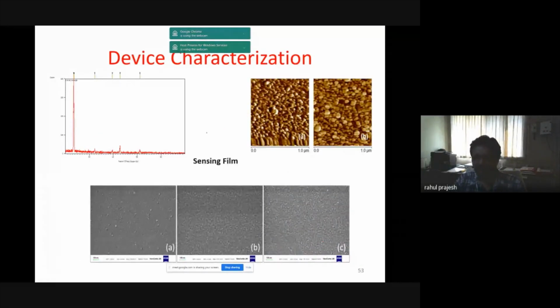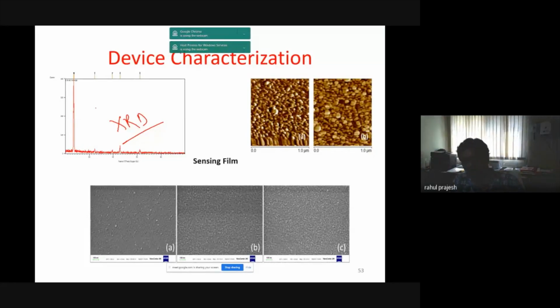Then comes the characterization of your film. In the film, what can you check? You need to first check your crystallographic orientation using XRD. XRD will tell you which planes are present. Is it a single crystalline film, a polycrystalline film, or an amorphous film? In most cases, polycrystalline films are much better for sensing application, and the XRD curve can tell you whether you have a polycrystalline or single crystalline material, and whether you are getting the required phase or not. Then you need to do the AFM analysis of your film, also the FESEM analysis of the film, so that you can understand the grain distribution, or the crystallites inside the film.